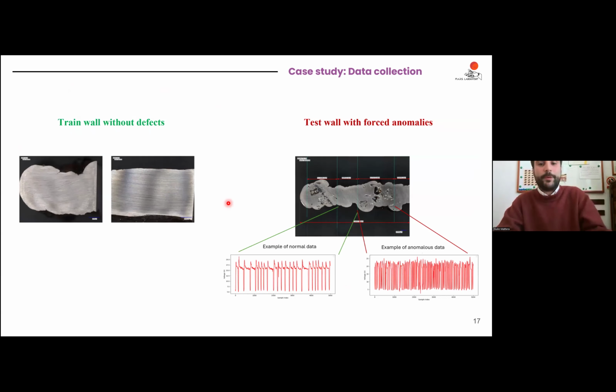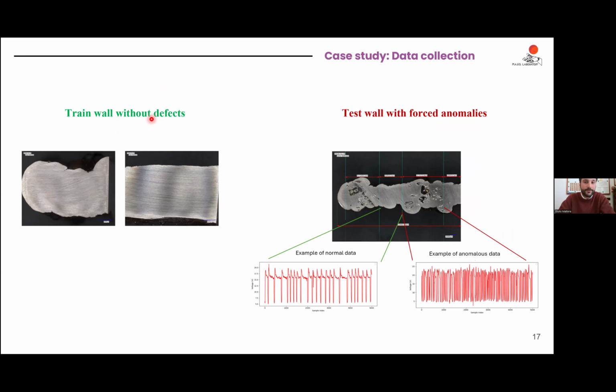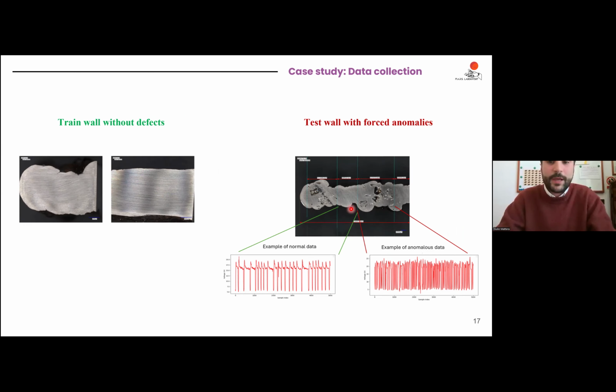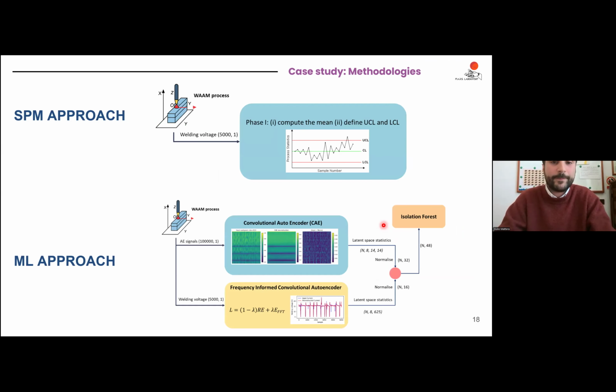And then you are going to deposit. When you deposit, you investigate the quality. This is a training wall without defects. Then you can force some anomalies, like missing gas or incorrect process parameters during the deposition, which can happen during a real process. Then you can collect the data for testing purposes for both normal deposition and abnormal deposition with defects. And then you can develop your machine learning approach.